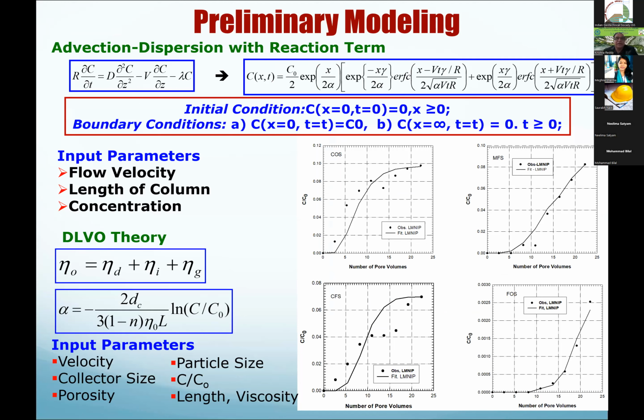So we did the modeling, so we used the advective dispersive equation with a reaction term. So this lambda term is there, and this is kind of general. So this is the governing equation. So you have diffusion, dispersion, advection, retardation, and reaction term here. The reaction term represents the trapping of these nanoparticles in the sand. So we have applied these initial conditions, boundary conditions. You get this solution, and then we try to model it and compare with the experimental results.